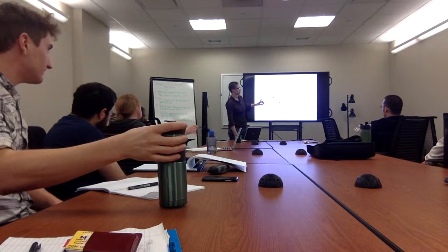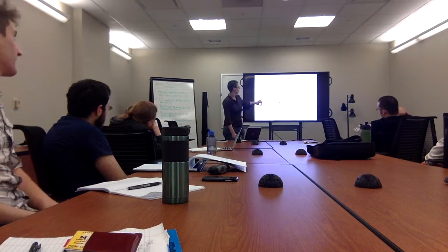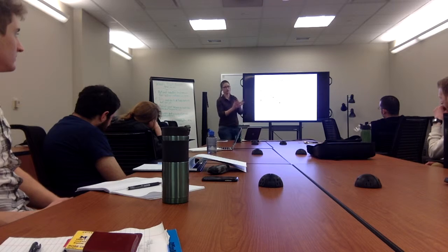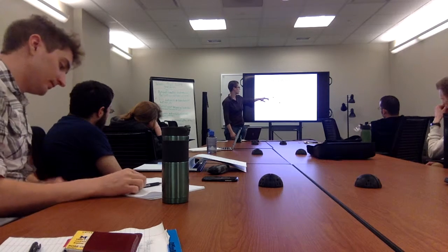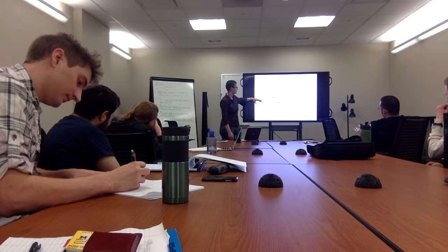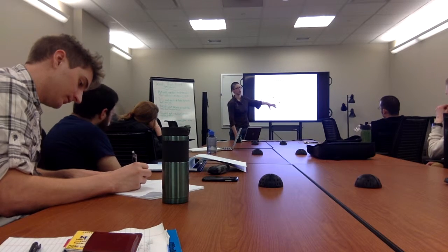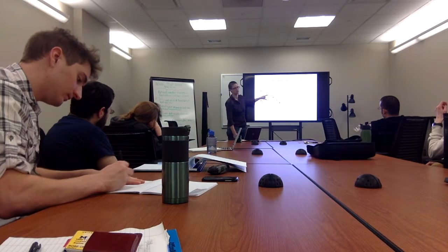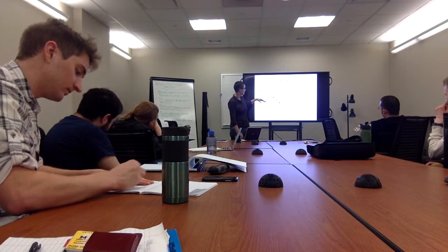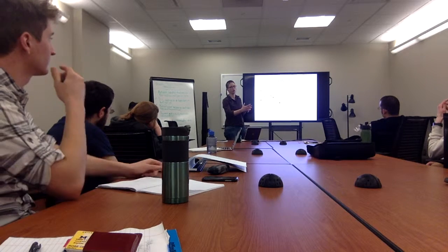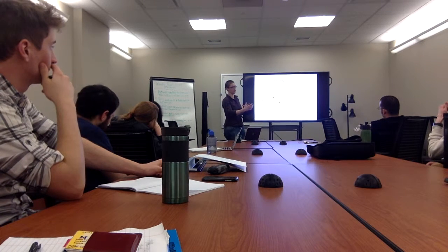And a lot of that is captured in thermodynamics by this paper that I like to talk about, where the black line is the energy situation for classic nucleation theory. But if you have some other pre-nucleation arrangement that can happen in the fluid, it can drastically change what the effective barrier to nucleation is. Say there are larger clusters of some other organization that can come together, then rather than having to nucleate with this disfavored surface arrangement, there's an arrangement that has a very small penalty or no penalty at all for forming in the fluid.